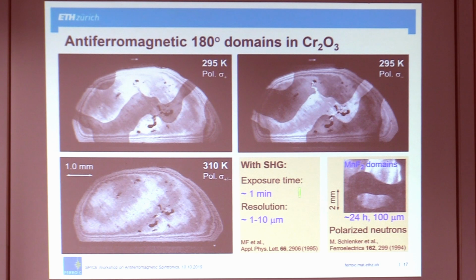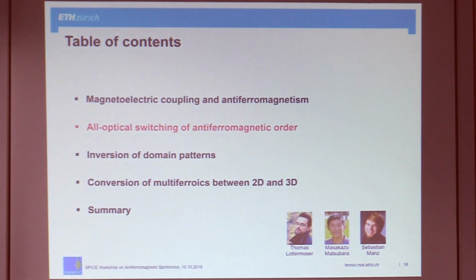That is really a shortcut to what you would otherwise have to do, namely work with polarized neutrons, and then after a 24-hour exposure, you can get a poorly resolved picture of antiferromagnetic domains. This is really very convenient if you want to image antiferromagnetic domains that are large enough. Okay, so then let's move on to the first example, what kind of antiferromagnetic systems we studied using this technique.